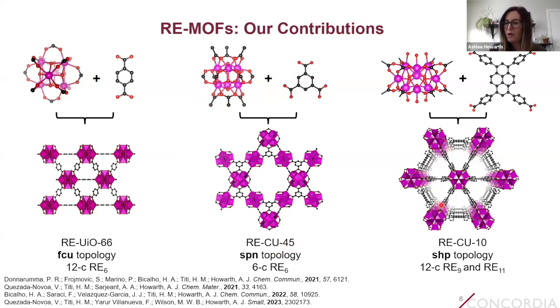We've also made a new MOF called rare earth CU10, where here we have a nonanuclear cluster building unit bridged by a tetratopic pyrene linker, and giving a MOF with the overall SHP topology, which I'll talk more about in a minute. So for all 3 of these MOFs, we've been able to make a large series of them using rare earths, including yttrium and lanthanoids ranging from europium to lutetium.